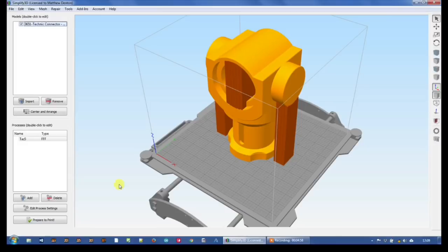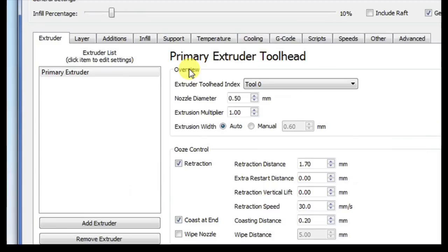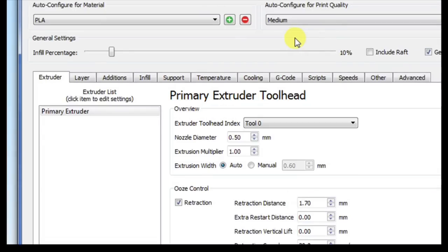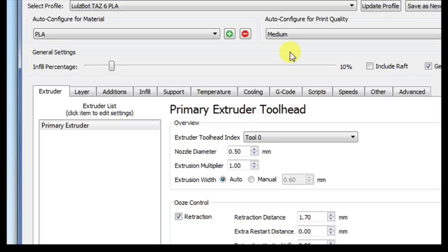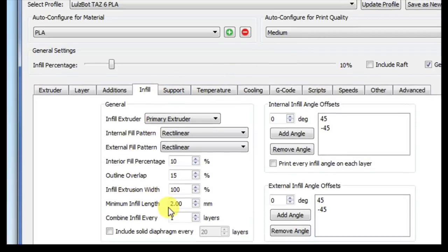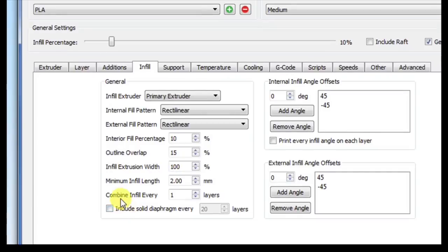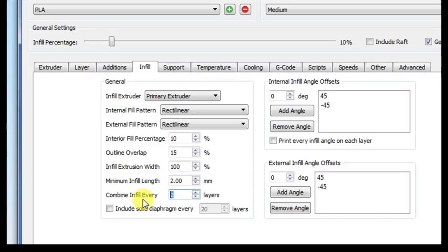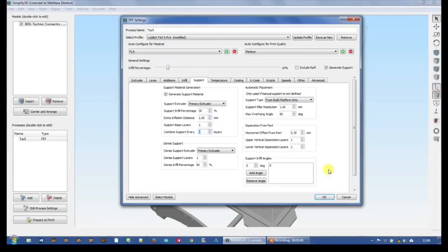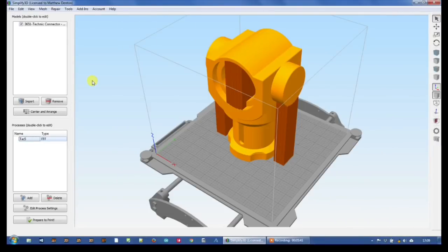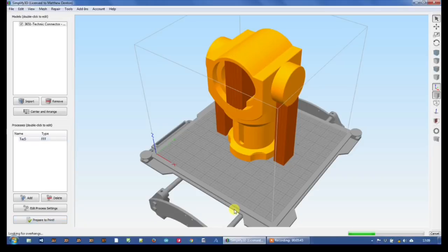We've saved some already just by getting rid of some of that support structure we know we don't need. But there's another trick, and that is because we are running in a resolution of 0.2mm with a 0.5mm nozzle, I can print a thickness up to 0.4mm layer height. So on the infill setting here, I can combine every infill, infill every two layers, so rather than doing an infill layer every layer, it skips them and does a thick infill of 0.4mm thick, which is fine because we don't need detail in the infill.